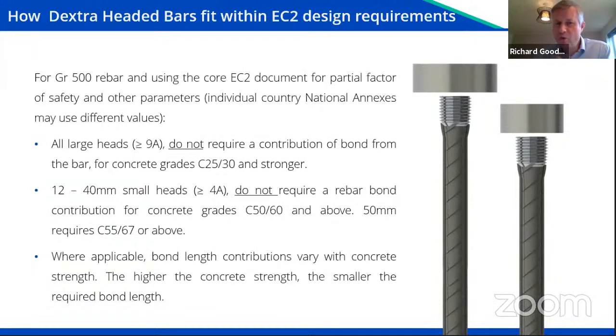However, if you use one of our small heads, you need a much stronger concrete, C50/60 or C55/67, in order to take the full load of the rebar via head alone. But in both cases, of course, you need to comply with the minimum spacing requirements that are calculated. And if you can't, effectively it means that you need to have a bonded length of rebar, or an increase in the bond length of rebar below the head.